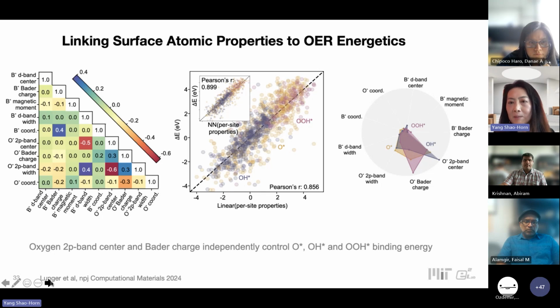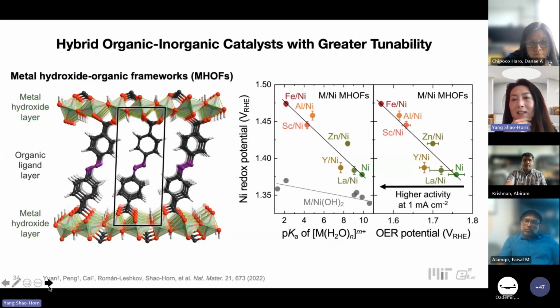And we can look at how these different electronic structures may influence the binding of various species. More importantly, what we learned is that if you look at the electronic structure influence on these three reaction intermediates, let's say O, OH, or OOH, they have very different dependence. This also suggests that if you only tune one electronic structure descriptor, we cannot really optimize these three reaction intermediates. So it requires different types of active oxygen sites in order to optimize the catalytic activity. This is one idea: we want to increase the local environment of oxygen to further tune the catalytic activity.